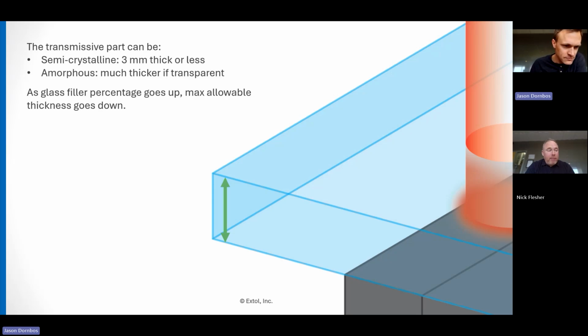You can also do light piping. We see this primarily in the automotive lighting space, where you can follow the contour of the part, just like they do in lighting, where you've got an LED generating light in a different spot and it's transmitting it down. So you can do the same kind of thing. If we're trying to weld down here, trying to get the laser energy to this spot, and this is the outer surface of that transmissive part, we're coming at it at some angle, right? At some angle, it's going to bounce away. So the trick is to hit it at the right angle so that it gets down here.